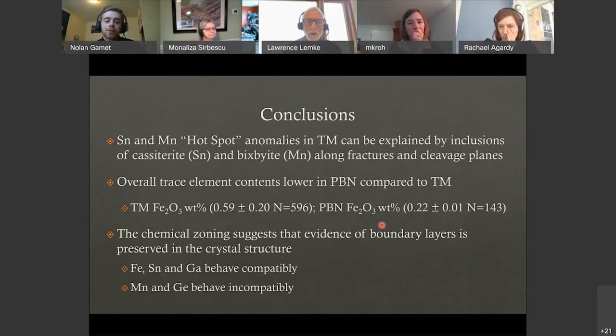The chemical zoning from the Abel maps and seen in the other data statistics suggests that the evidence of boundary layer was preserved in the crystal structure and was not affected by secondary processes and alteration. While tin, iron, and gallium behaved compatibly, manganese and germanium behaved incompatibly.